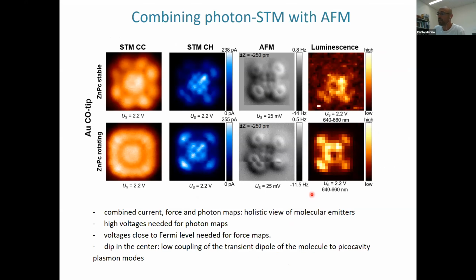Here I show that with this new instrument we can get constant height current tunneling maps, AFM and luminescence maps all together, which brings a holistic view of the electro-optical properties of the molecular emitter. Just to remark that for getting the photon maps, we need to use high voltages in order to trigger the emission, while for getting the force maps, we normally need to be very close to the Fermi level. Normally for photon maps in phthalocyanines, you have a dip in the center. Photon maps resemble the current, because there is a relation between how many charge carriers you inject and how many photons you excite. But there is normally a minimum in the center, which has to do with the inefficient coupling between the transition dipole of the molecule and the picocavity plasmon modes.